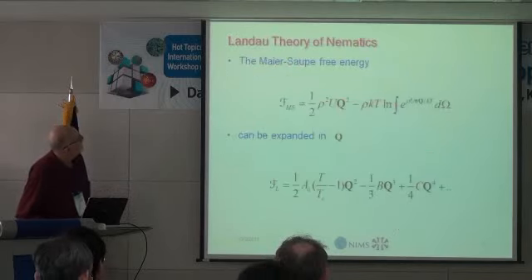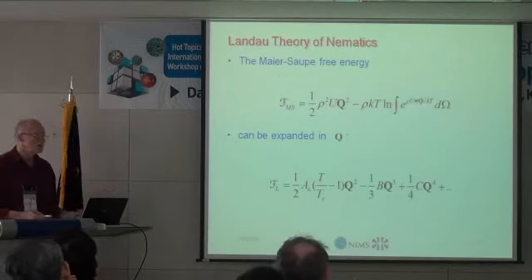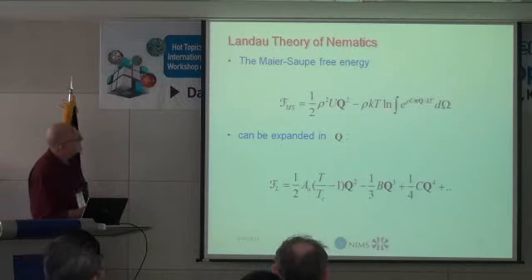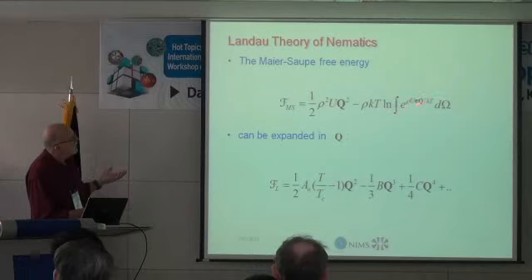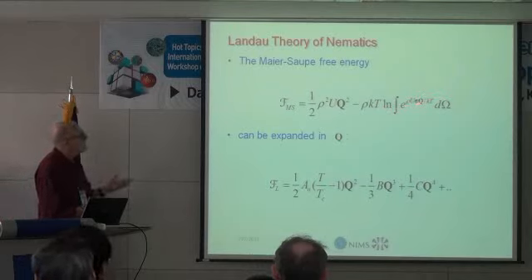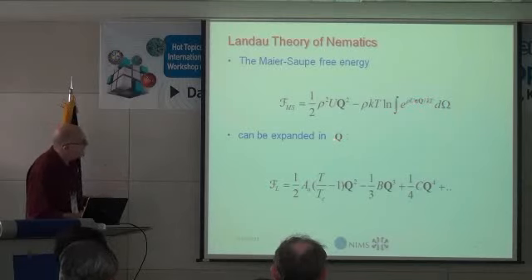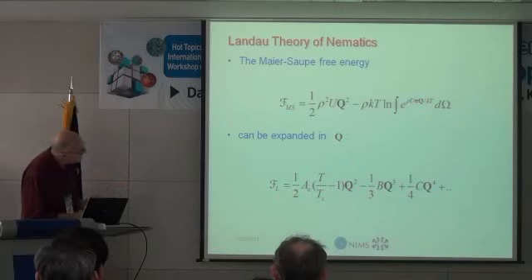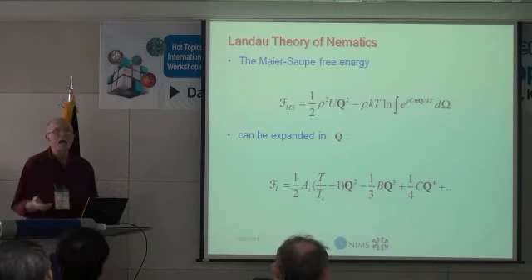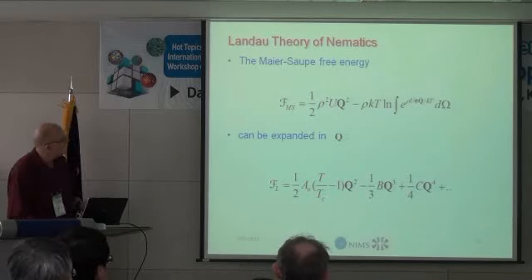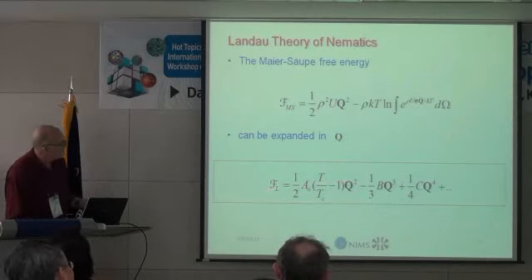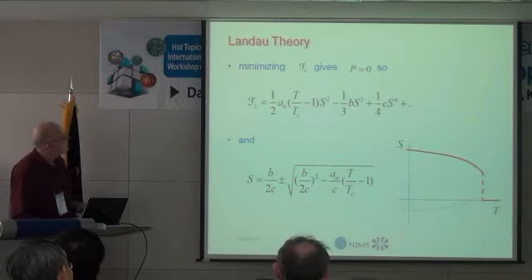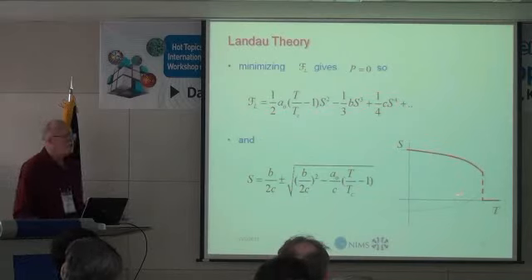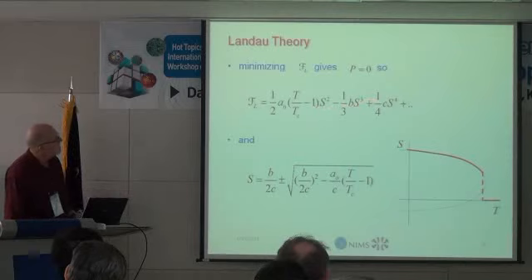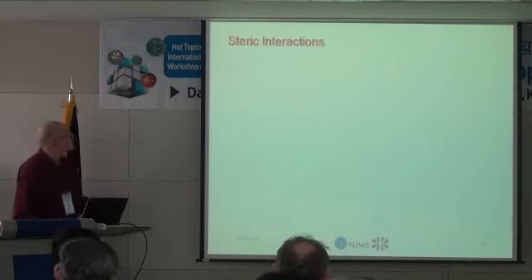It works like this. So now the Maier-Saupe description is very nice, but it's a little complicated with all these integrals. So one can simply expand this term here as a function in a power series, a Taylor series in Q, and then one gets a Taylor series expansion, which is called a Landau expansion. And interestingly, the coefficient of the quadratic term changes sign, and that is responsible for the phase transition as a function of temperature. So this kind of expression is called the Landau theory, and then one can again minimize this with respect to the order parameters and get essentially the same behavior with maybe a few more parameters that come from the expansion.